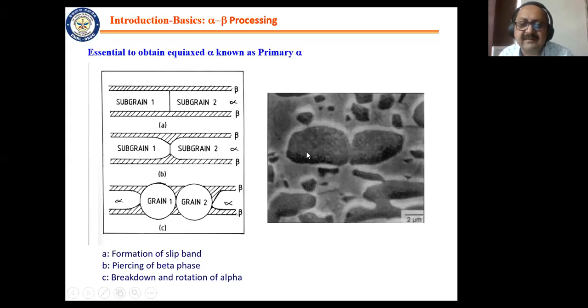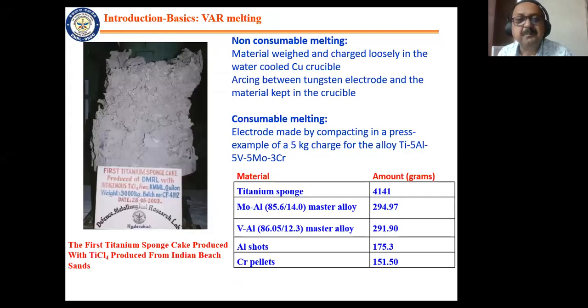This is many a time required for property requirements. I will talk about it again later, but this is very important. That is why many of the titanium alloys are given a lot of deformation in the alpha plus beta regime. Otherwise, you will not be able to refine and globularize the grain sizes. Once you take it to beta, again all this effect is lost. So again, in titanium alloys, you have to be very careful and monitor your temperature very well.